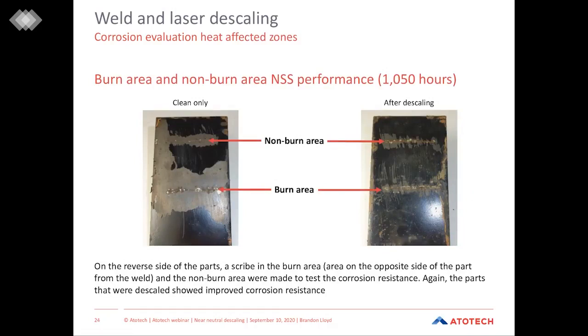Again, going back to what we referenced earlier about the burn areas. So these parts are welded. And if you look here, this area right here is actually on the back side of the weld itself. So this is the burn area that you would see from some of the other parts. What we also did is we did a scribe along the non-burn areas of these parts too, to evaluate what we would see from the performance in the non-burn areas. So what you can see from the clean only application is that the non-burn area does have some paint loss, but at the burn areas, we see significant paint loss and delamination of the e-coat paint.